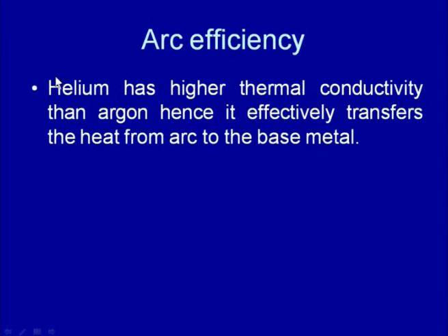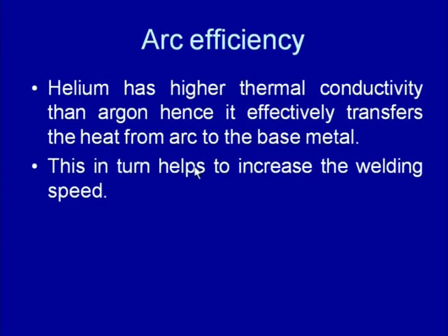Further, helium offers the advantage of high thermal conductivity over argon. The high thermal conductivity of helium helps in better transfer of heat from the arc zone to the base material, and thus permits more effective use of the heat being generated during welding for melting the faying surfaces, so that the weld joint can be obtained. And because of this, arc efficiency is found to be higher when helium is used as a shielding gas as compared to argon. So, this is what has been mentioned. Better transfer of the heat from the arc helps in rapid melting of the faying surfaces, which in turn allows us to go with a higher welding speed.